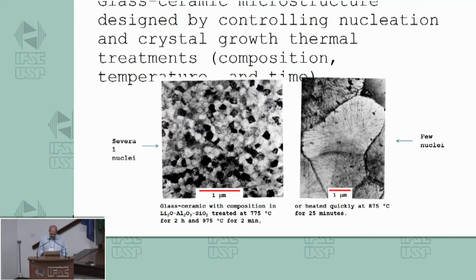But the same glass can be obtained in a different microstructure with a few nuclei, letting less time in the nucleation step. So as we have a larger distance between nuclei, the crystals can grow more, and we have a coarser microstructure. So we can manage to control the microstructure, the crystallized fraction, then the size of the crystals in the microstructure. That's not, in a way, possible using the traditional ceramic method, by the powder technology.